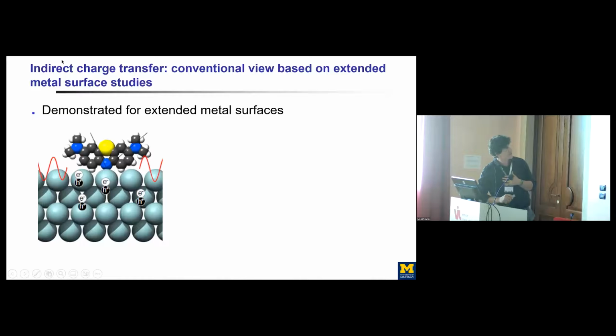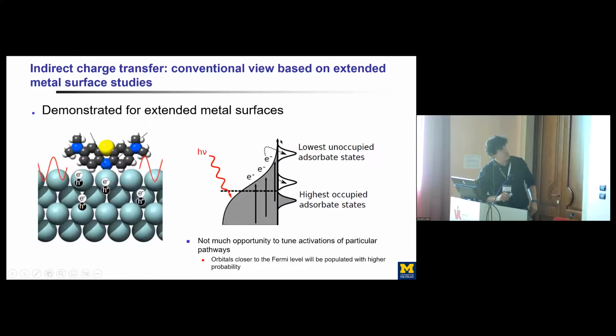And the idea here is that, again, as I said before, you shine light, you create electron-hole pairs in the bulk. These electrons are colliding with each other, and basically you get something akin to an electronic temperature. And then out of this distribution of electrons, you have electrons that are scattering through these orbitals. So this would mean that the closer the orbital is to the Fermi level, the more electrons you would have at that energy, and therefore you would have more scattering for an orbital that's closer to the Fermi level.